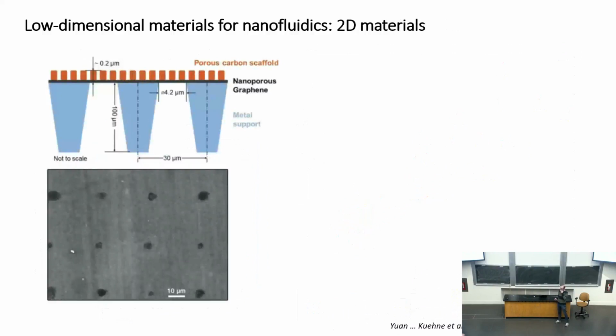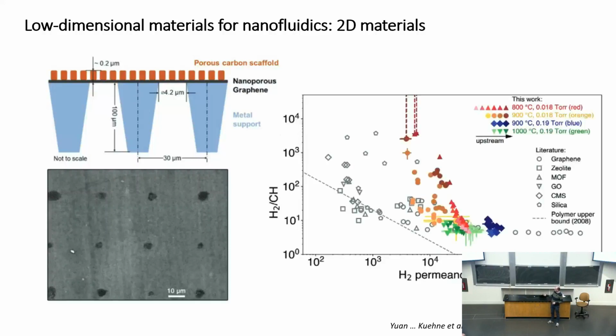Another development is 2D materials. Since graphene, there has been a lot of work there. We have been working, for example, here on graphene that we grow by chemical vapor deposition, and we actually make defects in the graphene during the growth immediately. And so the grad student, who was the lead author on this work here, did a careful job in basically growing a lot of defects but keeping them small, in an atomically thick membrane. This sparks the hope that we can have very high selectivity, at the same time very high permeance.